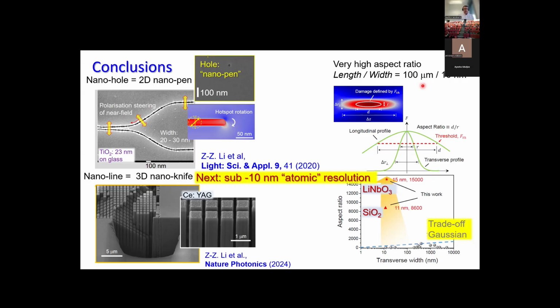Yeah, it's a good question. These days, femtosecond laser machines are really very stable. Some results here were obtained with the old titanium sapphire laser, which was less stable, at only 1 kilohertz. But some results were done with the newer versions of Light Conversion units, which are well enclosed in these machining setups. They are not really susceptible to changes of their output power. They are very stable. That's why we can reproduce a single shot making the same nanohole each time we shoot. And I know from the companies that there are examples where many holes for fibers are made inside a silica wafer. The tolerance for mistakes is simply non-existent. They need every shot to produce the hole, or expose the volume which is later etched out. So the short answer is that lasers have the required stability now.